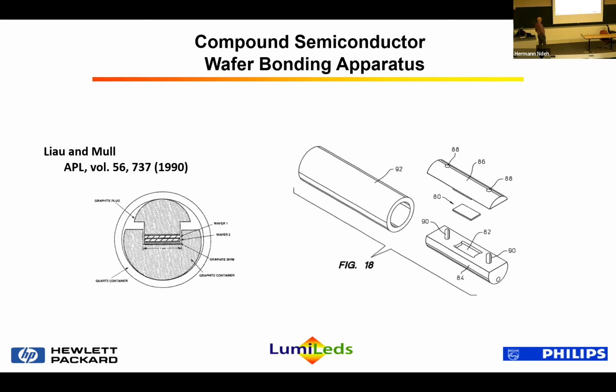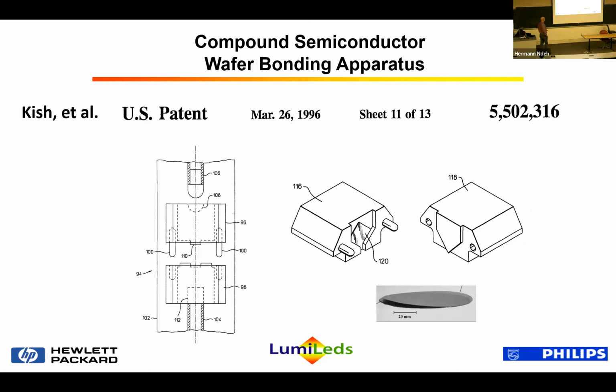So we looked at that output and said, gee, if we could develop this technology further, this could be something that could be really useful to what we were trying to do with visible LEDs. So we developed a tool and a capability that was able to independently apply force and temperature. So two graphite anvils, and in this case, they're in a modified LPE furnace where we apply pneumatic pressure and can independently apply force and temperature.